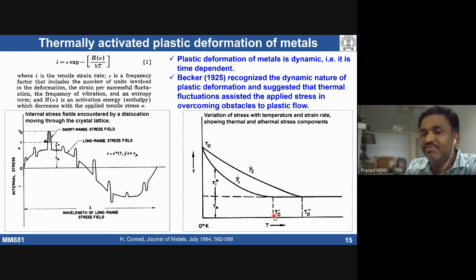With increasing temperature, at a given particular strain rate, the stress required to overcome thermal barriers is going to come down, but the stress required to overcome the athermal barrier is not going to change. After a certain temperature, the stress required to overcome all the thermal barriers is going to be zero. That means I need to apply only the stress required to overcome the athermal barriers. Depending on strain rate, the higher the strain rate, the higher the thermal stress I need. The athermal stress is not going to change, only the thermal stress changes depending on the strain rate.